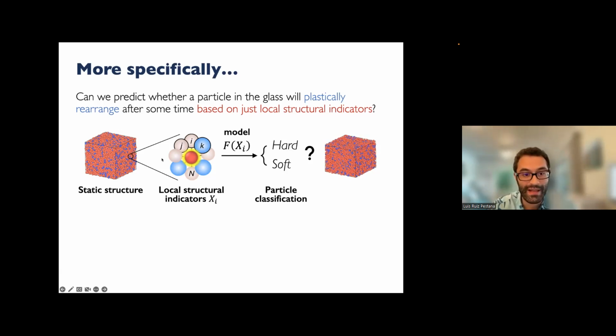If you take one particle in the glass, okay, and it's this red particle with a yellow boundary, we can build local structural indicators. What that means is metrics that describe the local environment of this particle. The idea is, can we build a model, some function of those indicators, that can tell us if that particle will plastically rearrange or not. We'll talk a little bit more about what this plastic rearrangement means, but in a very general sense, you can basically classify particles in two types. One is hard. These would be particles that upon deformation don't displace a lot. They are actually moving in their own local minima. And then soft particles are those that undergo large rearrangements, and we call those plastic rearrangements.